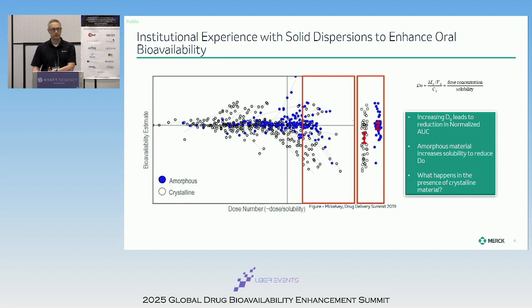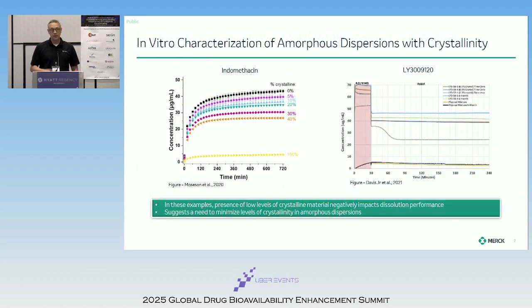And what you see along the x-axis is increasing dose number, and what we see along the y-axis is a bioavailability estimate. And so these negative deviations that we're seeing as we go out in terms of dose number are reflective of when you get to a critical dose number, you can no longer support that product with a conventional formulation. And by going ahead and leveraging amorphous dispersion technology to increase the solubility, we're able to bring the bioavailability estimates more in line with the linearity that we would have projected from the lower doses when we administer at higher doses. But this begs the question of what happens when you have low-level crystalline material in your solid dispersion.